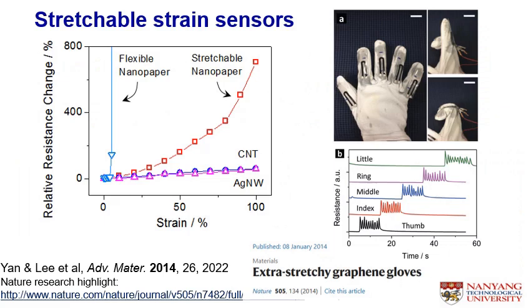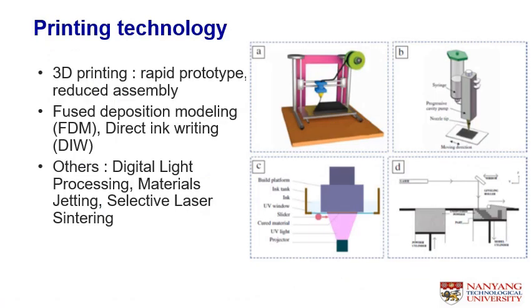Compared to the nanopaper without the crumpled graphene, the flexible nanopaper show a surge in the resistance without a systematic piezoresistive behavior. While if we change the crumpled graphene into carbon nanotube and silver nanowires, the sensing performance or sensitivity is not high. The strain gauge factor here is relatively high compared to other materials, and it can be used in wearable, for example, in a smart glove that has embedded with the strain sensor. However, the work is not utilizing any printing technology that can allow localized deposition and patterning.